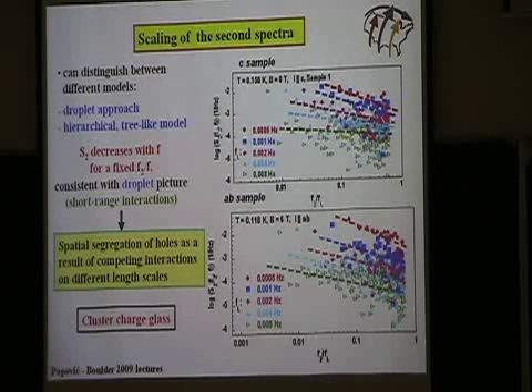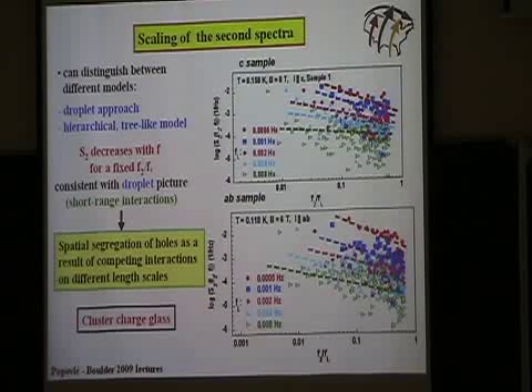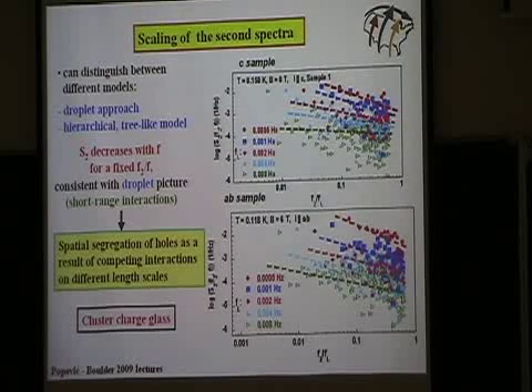So what we conclude is that this charge glass is somewhat different. This is a cluster charge glass. And I also want to mention that the spin glass in these materials is not the same as spin glass in conventional spin glasses. It is also a cluster spin glass.